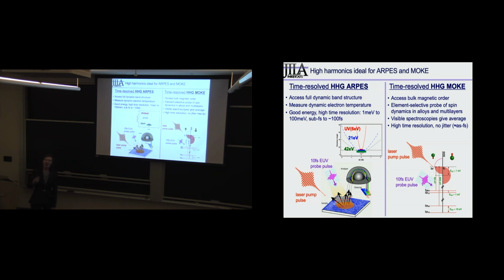But we started to get some hints that when we applied the regular spectroscopies, we weren't actually seeing what was going on in the material. So we started a campaign where we did multiple spectroscopies on the same sample. It is very easy with the same high harmonic source to implement time-resolved ARPES and time-resolved magneto-optic spectroscopies, and they probe very different things about the sample.